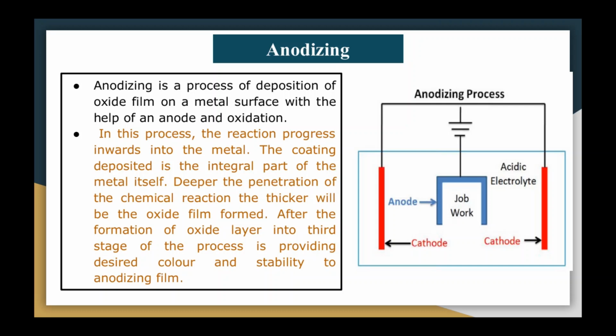When current passes through the electrolyte, a chemical reaction takes place and oxygen is liberated, which reacts with the metal surface to convert it into an oxide. In this process, the reaction progresses inwards into the metal. The coating deposited is an integral part of the metal itself. So the deeper the penetration of the chemical reaction, the thicker will be the oxide film formed. After the formation of the oxide layer, the third stage of this process is to provide the desired color and stability to the anodizing film.